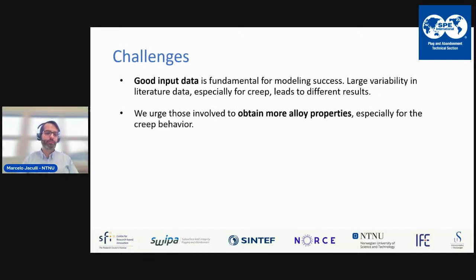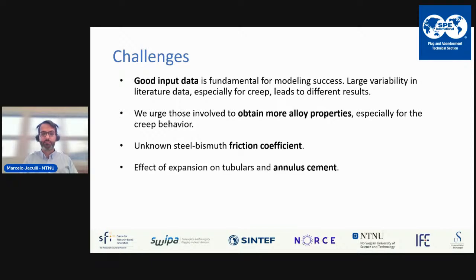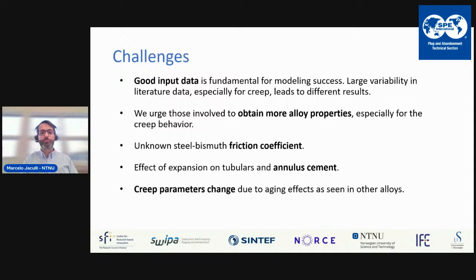We recommend that those involved obtain more alloy properties, especially for the creep behavior, because that defines the maximum operating temperature we'll be able to put our plug on. We still don't know much about the steel-bismuth friction coefficient, so that needs investigation. We also don't know much about the effect of bismuth expansion on tubular and annulus cement, which we wish to investigate further. Creep parameters also change due to aging effects, so those effects are also coupled, which could lead to further modeling complications.